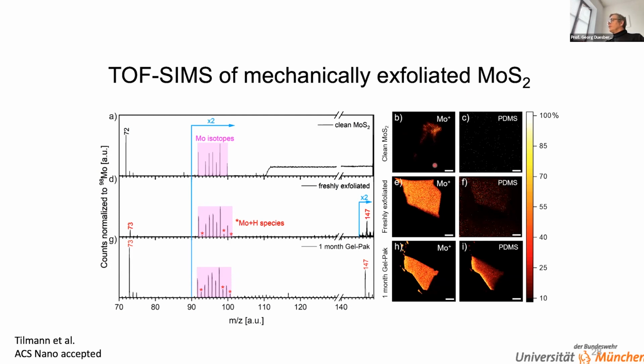This is a molybdenum peak for the flakes, and this is a PDMS peak for this clean sample, the directly exfoliated sample brought to the machine, and this is a PDMS peak on a flake which had been stored in a gel pack for about a month. Interesting to note is that the PDMS seems to preferentially adsorb onto the MoS2 flakes.